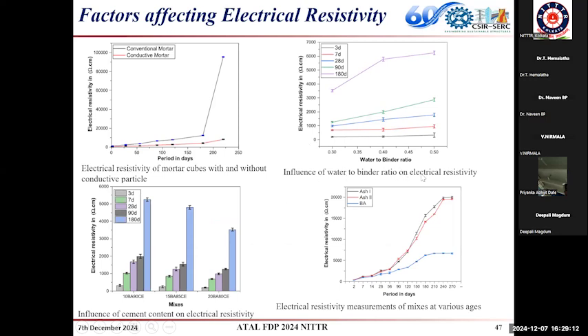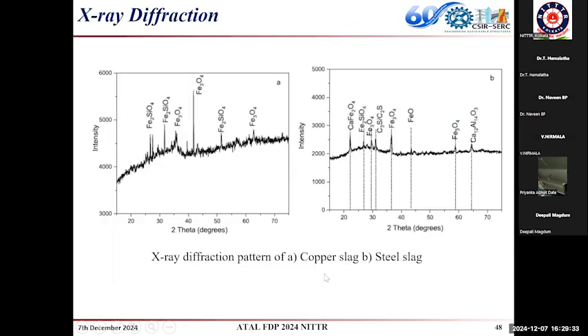Here is how the water binder ratio influences the resistivity at various ages from 0 to 270 days. And here is how the cement content, when we are replacing it with bagasse ash, influences the electrical resistivity. And these are 2 different types of slag. We have used copper slag and steel slag. The Fe2O3 iron oxide content is in different forms, and it is providing resistivity. So this knowledge we can receive by characterizing the material.